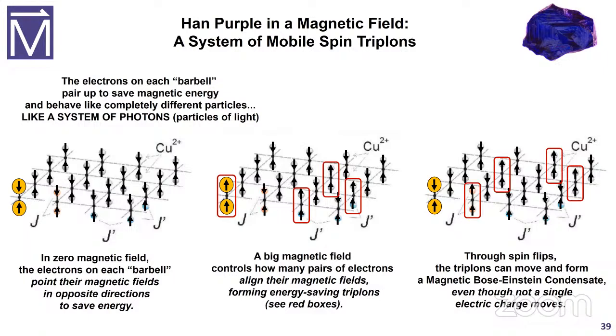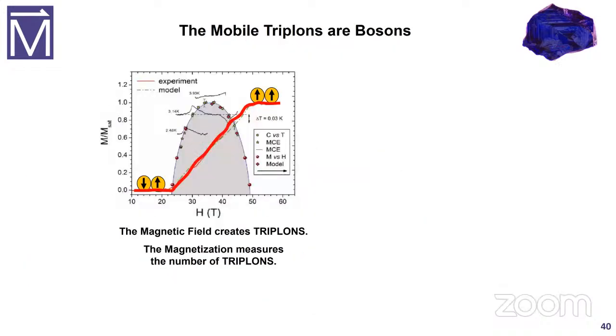And through simple spin flips, you can move the triplons. It can move from here to its neighbor just by flipping that spin and flipping that spin. So flip two spins, doesn't cost energy, and your triplons can move. They can move, and because they're bosons, they can form a Bose-Einstein condensate, even though not a single electric charge is moving. So the magnetism is in red. And the magnetism tells you how many aligned spins you have. You start with zero until you get to 23 Tesla. You get more and more and more of them until you get to 50. And above 50, they're all spin aligned.